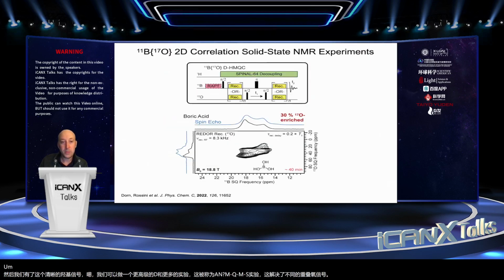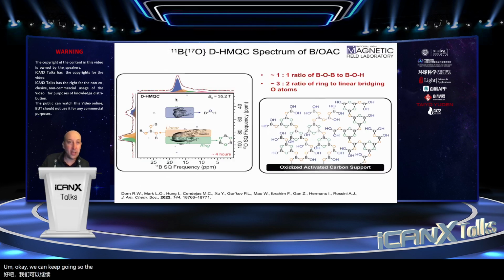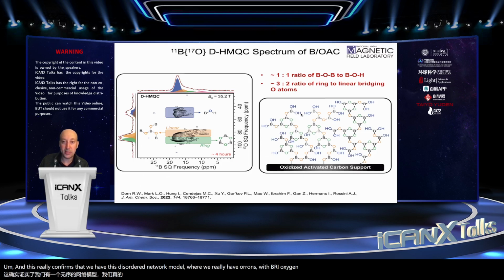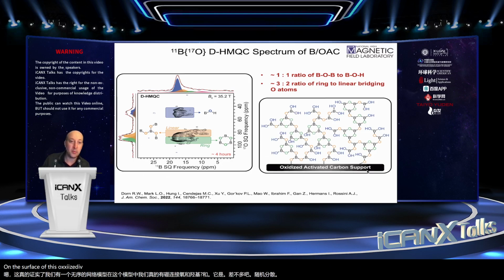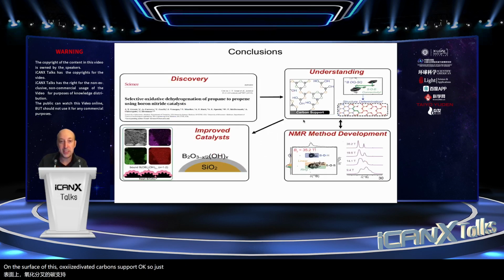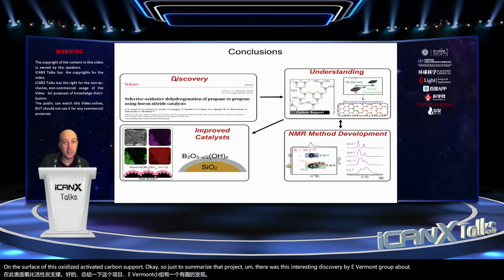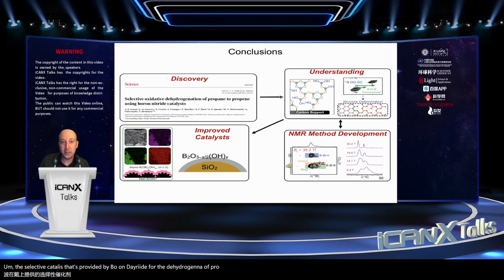Okay, we can keep going. The other thing we can do here is then do a boron-oxygen 2D correlation experiment. And this really confirms that we have this disordered network model where we have borons with bridging oxygens and hydroxyl groups, and it's all kind of randomly dispersed on the surface of this oxidized activated carbon support. Okay, so just to summarize that project, there was this interesting discovery by Eve's group about the selective catalysis that's provided by boron nitride for the dehydrogenation of propane. If we do some NMR experiments, we can gain some understanding of the structure, and then we can use that information to design improved catalysts.